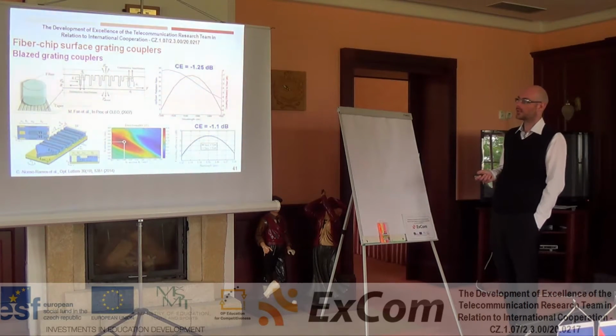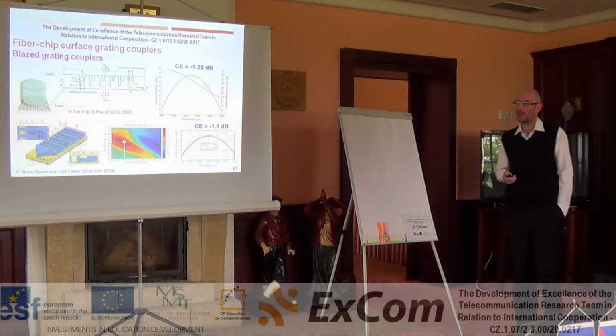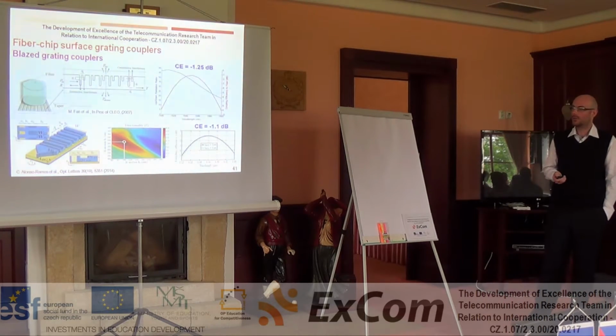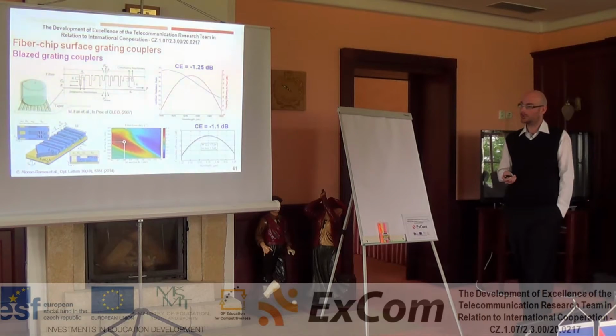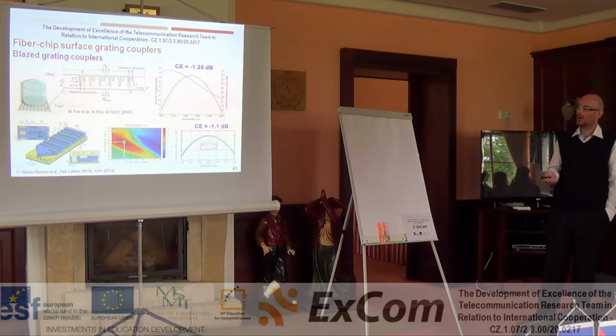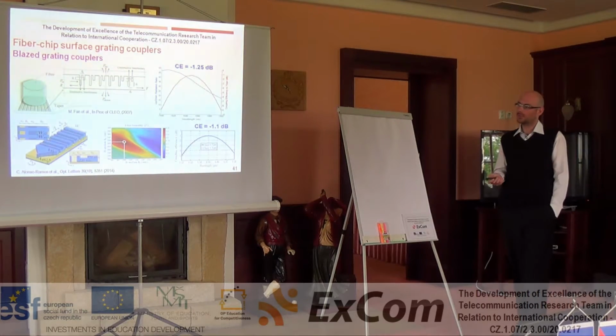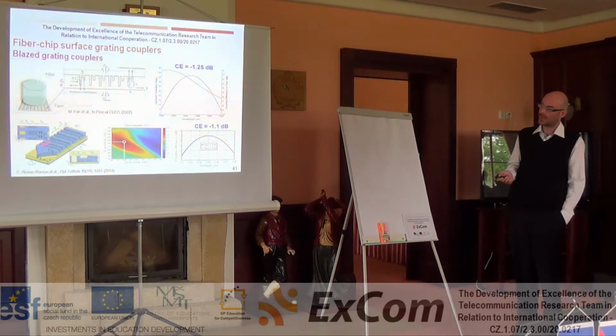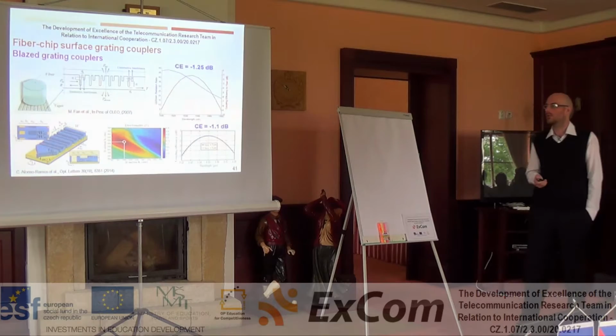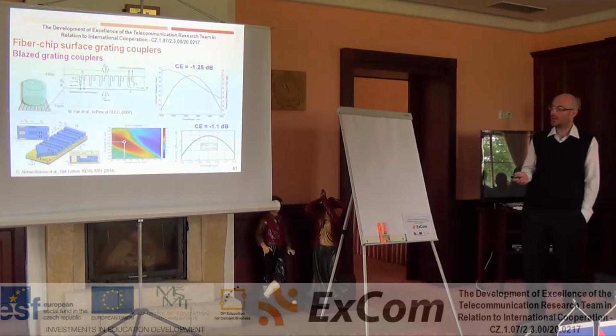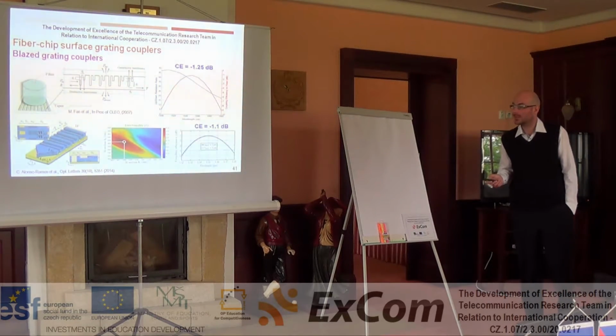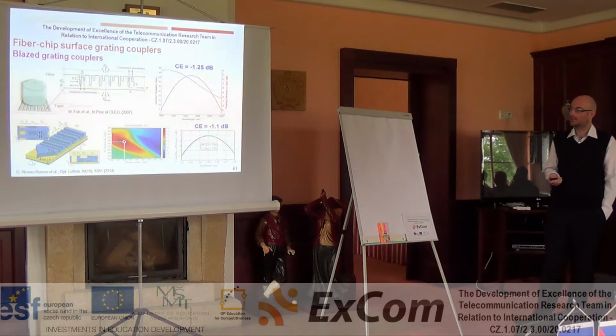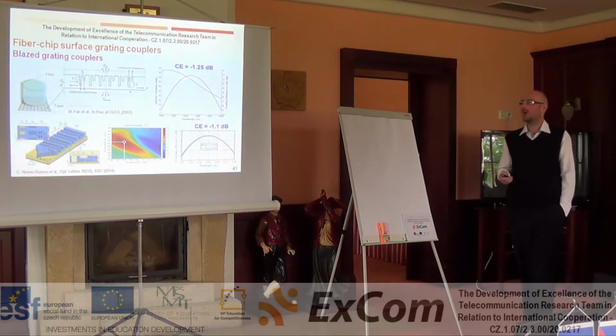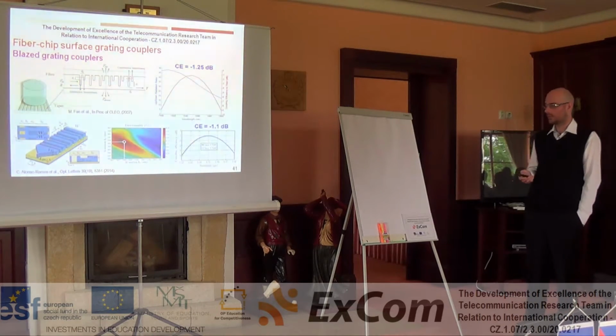A very nice approach has been proposed by Dr. Ramos from University of Paris Sud. They use a CMOS compatible process with etch depths that are typically used in silicon photonic foundries. In this way, they achieved a very impressive coupling efficiency of -1.1 dB.